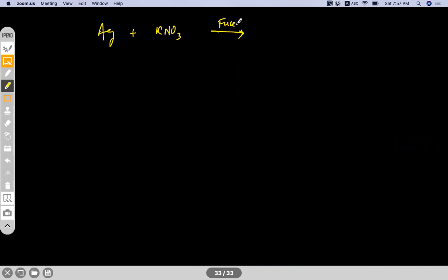So Ag plus KNO3 will have the fusion now. This black precipitate converts into silver metal, and all the impurities will get oxidized and rise as scum, which we can filter out. The impurities we can remove like that. So we'll get silver metal after cooling.